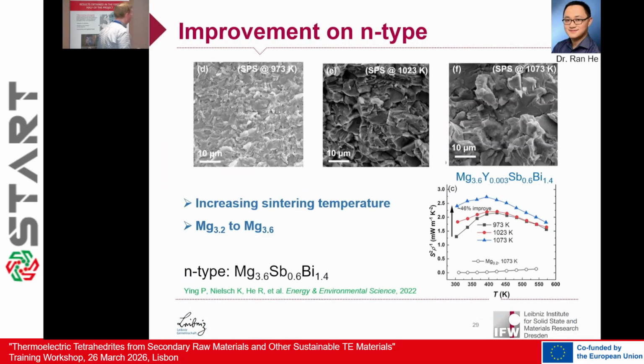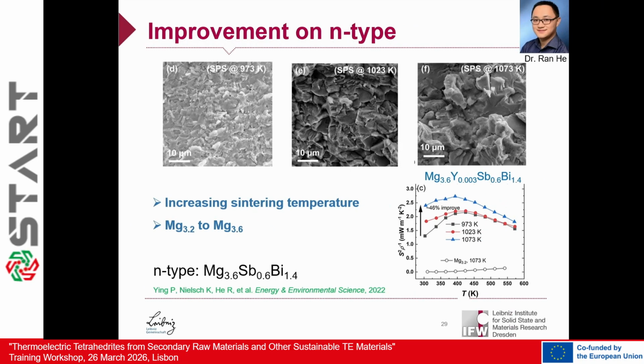And this can be optimized by changing the compaction conditions. So we use spark plasma sintering, and we applied different temperatures, for example. And you can see here that when we apply 100 degrees more, we have larger grains, and then the power factor performance is much higher. And you see also in this formula, 20% excess of magnesium is used when we apply the higher temperature. So we have some loss of magnesium, but there are also some ways, in future, we might even work with smaller excess ratios of magnesium in the production.